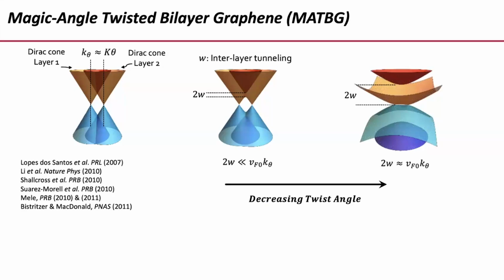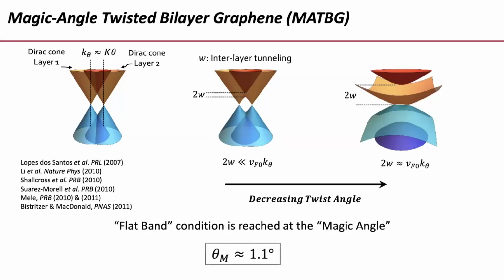Okay? And that happens when this interlayer tunneling is approximately the energy of that crossing point, yeah? So we say that a flat band condition has been realized and is reached at an angle, which depends on that interlayer tunneling, and which was coined by Rafi, who's here also, and by Allan as the magic angle, okay? And it happens to be 1.1 degrees for graphene on graphene. So this was the famous prediction that Allan worked on together.